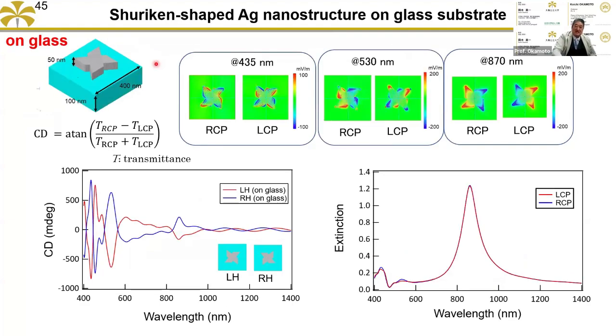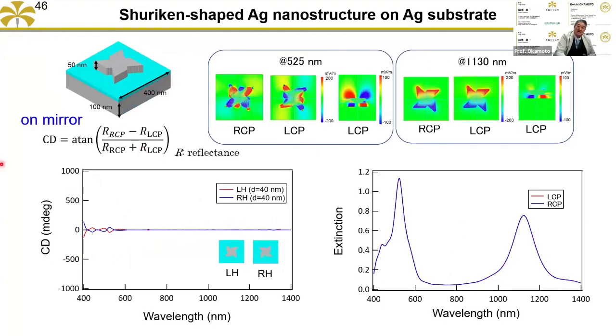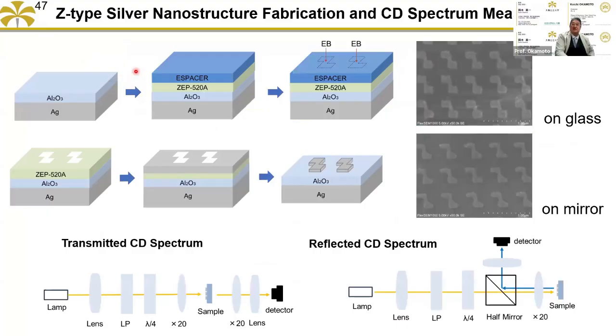Another interesting case is a four-fold symmetric structure, a shuriken structure. In this case, initially it has some CD, but with the mirror interaction, the CD was completely gone. That's why we can enhance or reduce the CD by controlling this nanostructure. That's the simulation, and we fabricated this structure by EB lithography and measured the CD for the transmitted and the reflected spectra.